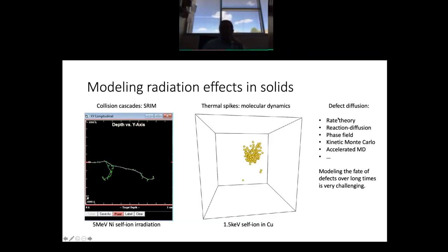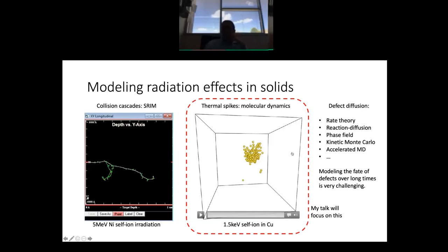And then once you've created defects, modeling how those defects interact with each other and with the microstructure, modeling the fate of those defects over long times, that's something that's very challenging. There are multiple approaches to it. I've listed a couple of them here: rate theory, reaction diffusion equations, phase field modeling, kinetic Monte Carlo, accelerated molecular dynamics, just to give a few examples. This is a very, very active area of research. I would say that the majority of computational research in radiation effects is occurring in this area of looking at defect diffusion. But I'm going to focus my talk, as I said, on this thermal spike phase, which is pretty well described by molecular dynamics.